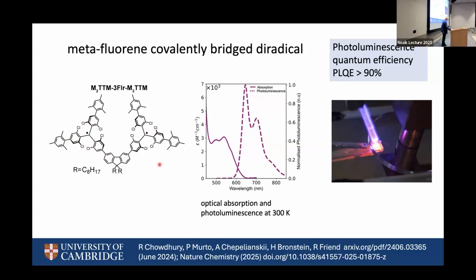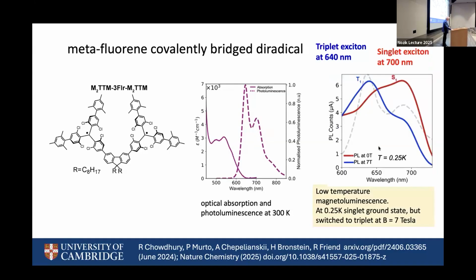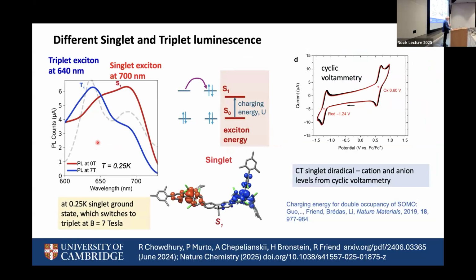where we can control how much interaction there is between the two spins. What we see in the luminescence are two bands, one at about 640, so that's deep red, and one at 700 nanometers, which is out in the infrared. And you might think that they have the same origin, that one was a vibronic overtone of the other. And by the way, the luminescence is bright, so blue laser light coming in and red luminescence coming out very, very liberally, and they're easy to see. But remarkably, that isn't what's going on. What we're actually getting are two different emissions from whether or not the two spins were parallel to start with